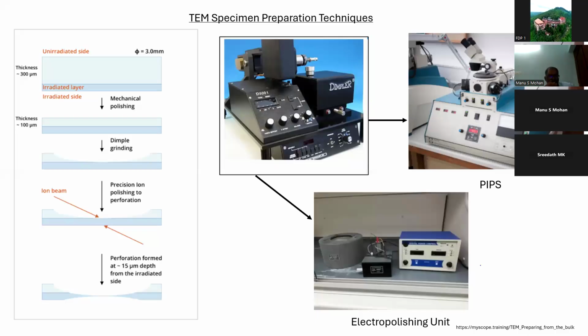Whereas TEM, it cannot be. It is not like that. However skilled you are, it may need almost half a day or more than that. Sometimes almost one day. The reason is that if you are hasty or very quick, then what happens? You will deliberately induce artifacts. There is a higher chance for dislocations or other defects to be introduced in the specimen. So it has to be carried out very slowly. The specimen has to be prepared carefully.